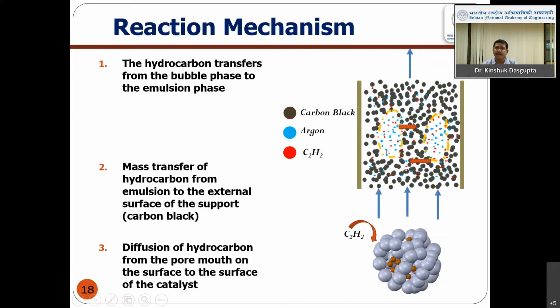So what is happening? There are two phases in the fluidized bed. One phase is called the emulsion phase, where the carbon black agglomerate and the gas are homogeneously mixed, and another phase is called the bubble phase, that means excess gas. In the bubble phase, the argon and hydrocarbon are present in excess.